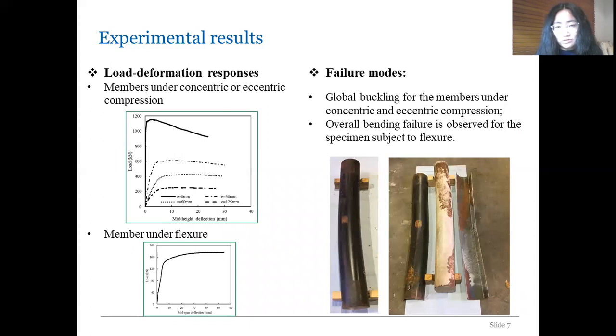Failure modes of the structures were also observed from the test. Global buckling happened to the members under concentric and eccentric compression. Overall bending failure was observed for the specimen subject to 3-point bending.